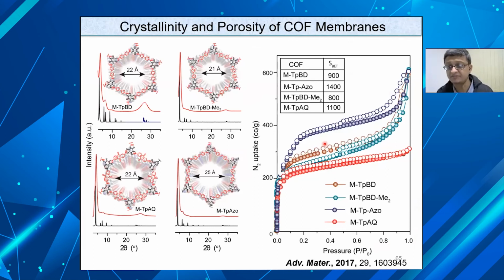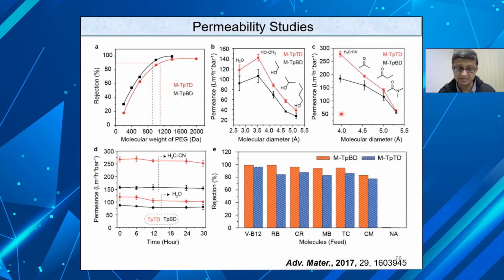You can see this thick film is about 1,000 meters squared per gram porous, which is really stunning, because generally the thin films or thick films are not up to that porous, because you can see the organization of the porosity is completely broken. We could do a size selective separation once again, and you can see over here in molecular weight, this is the PEG, which should not have any molecular cutoff, but we could still see a nice cutoff of the PEG molecules as well.